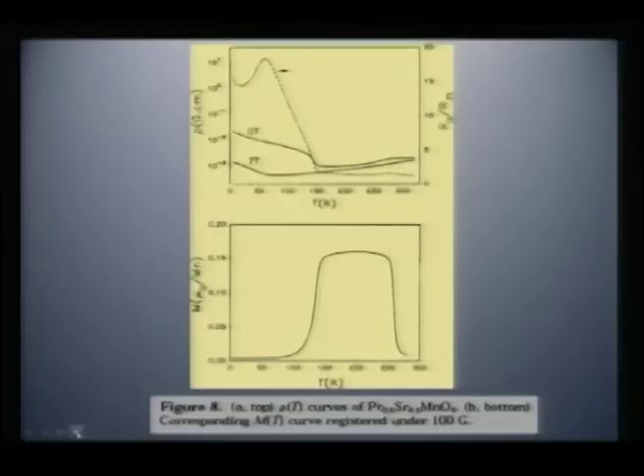This is another very interesting case where you see praseodymium is in a charge ordered state, because you have substituted up to 0.5. Therefore, this is a charge ordered situation where this is your ferromagnetic transition and this is your antiferromagnetic transition. So, from a paramagnetic it goes to a ferromagnetic transition and then it comes to an antiferromagnetic transition.